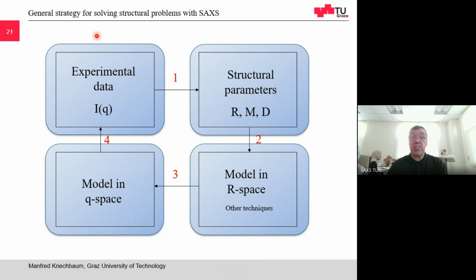So the general strategy for solving structural parameters in small angle scattering is that way. You have your experimental data. You evaluate the structural parameters like radius or radius of gyration. You can determine also the mass and the maximum diameter. So size, mass, and diameter. And then you make a model in the real space. You transform this model back into reciprocal space, into your experimental space where you got your scattering curve, and then you compare it with your experimental data.